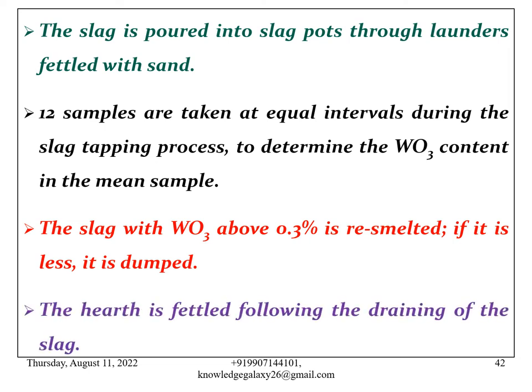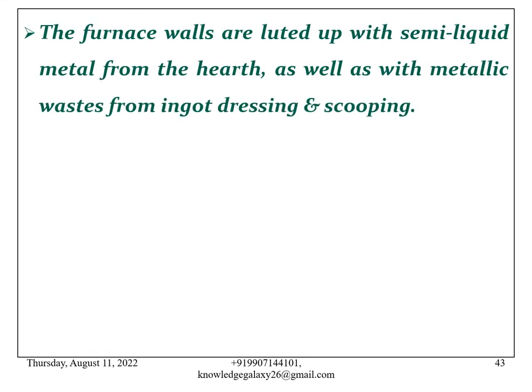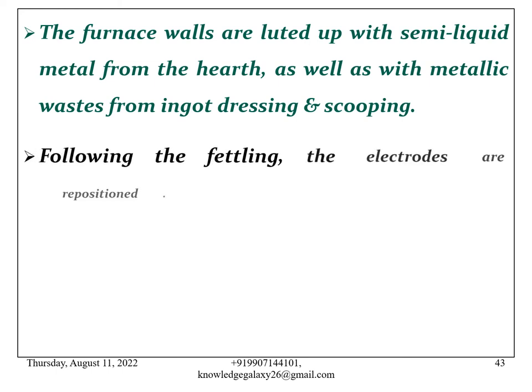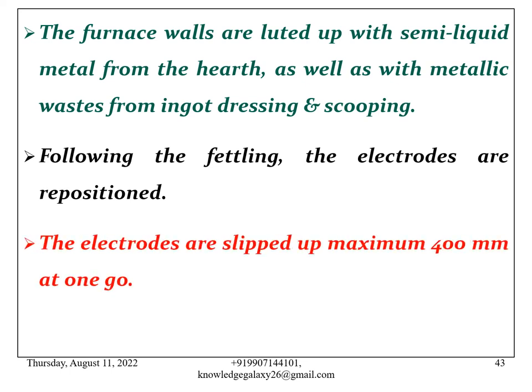The slag with WO3 above 0.3% is re-smelted, and if it is less, it is dumped. The hearth is fettled following the draining of the slag. The furnace walls are luted up with semi-liquid metal from the hearth as well as with metallic waste from ingot dressing and scooping. Following the fettling, the electrodes are repositioned. The electrodes are slipped up a maximum of 400 mm at one go.